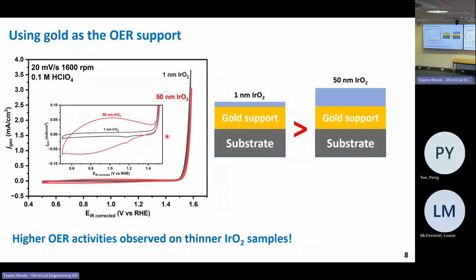Yeah, so from this, 1 nanometer iridium oxide outperformed 50 nanometers of iridium oxide. But surprisingly, we can usually estimate the electrochemically active sites by the non-Faradaic capacitance. So 50 nanometers of iridium oxide has a larger capacitance, but we don't know why it behaves worse than a thinner one. Maybe the conductivity effect is more pronounced at a thicker sample, because iridium oxide is less conductive than gold, or there is some size effect because it's like really small nanoparticles.